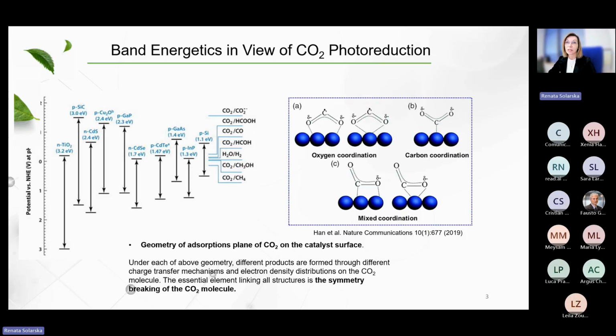So it becomes clear that we need a hybrid system where the weaknesses of the material are compensated by the improvement of the surface or by a complementary second phase. Here you can see the copper oxide morphology, since we chose this material as a base material. The reason is that copper 1 oxide is able to carry out the reduction of CO2 towards C2 products. So you see the morphology, which is very good for the photoelectrochemical reduction of CO2 and allows impregnation and entrance of CO2 intermediates within the semiconductor structure.